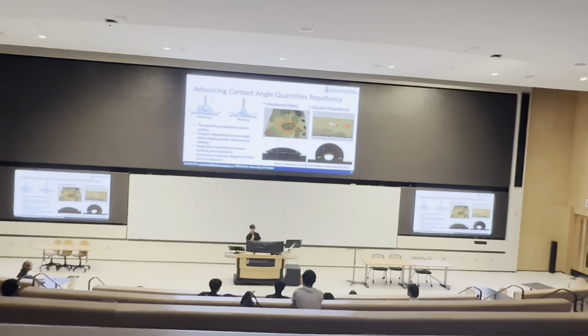In order for a liquid to wet the surface, it must first advance. So if you can take a look at the two fabrics that are shown on the right, one is uncoated, and one is coated. You can see with the uncoated one that it gets wet when a droplet is deposited on, and the angle is 0. But for the coated fabric, it's extremely high, like 120 degrees. And so this is especially important because, yes, we want the substrates to not get wet when coated, but it's especially important for porous substrates like fabrics because they can get wet, and on top of that, the liquid can actually go through the substrate.